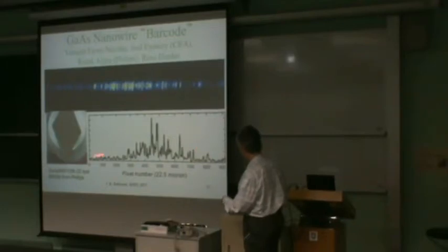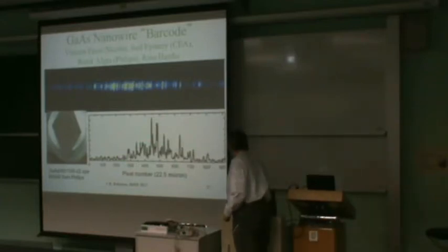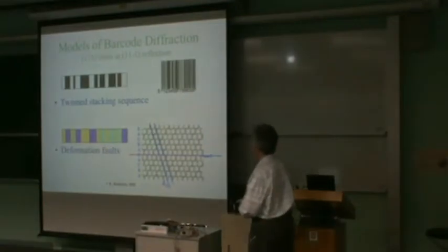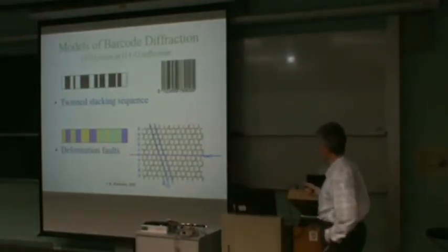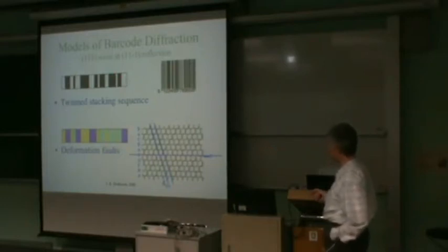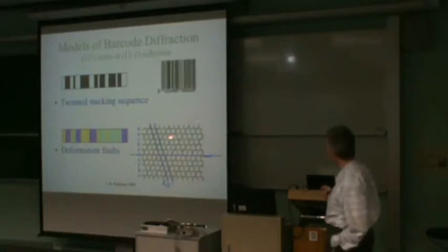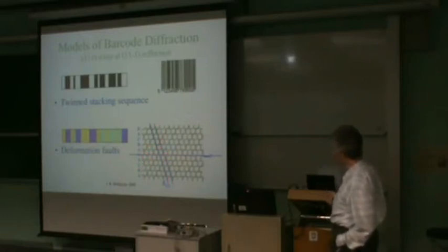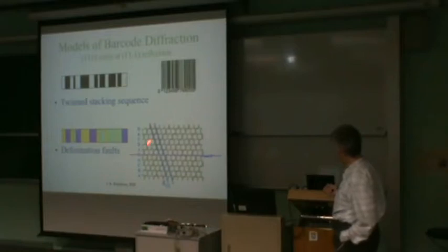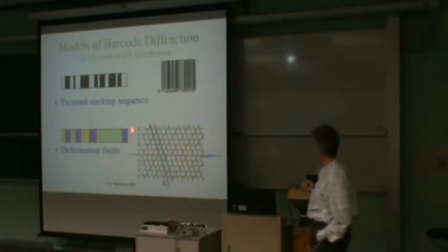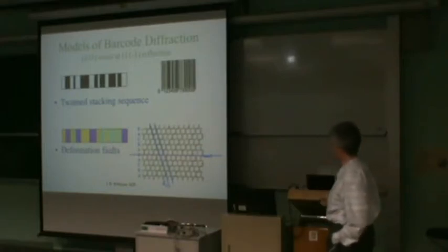This is the diffraction pattern we're working with, and it's a one-dimensional diffraction pattern of a sequence of stacking faults in the wire. So the way we understand that is, well, two possible models, but we're pretty sure this is the correct one at the bottom. You have stacking faults which occur in, this is gallium arsenide, but it looks just like silicon. When you have a stacking fault in the vertical direction in the screen here, then the phase of the off-diagonal 111 reflection changes by 1/3 of 2 pi. And so you get a 1/3, 2/3, and 3/3 phase shift for every one of the stacking faults that's introduced along the length of the wire.